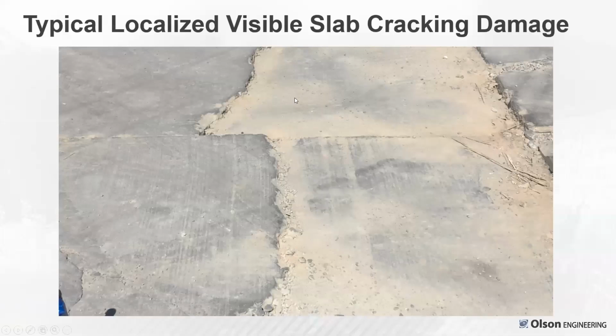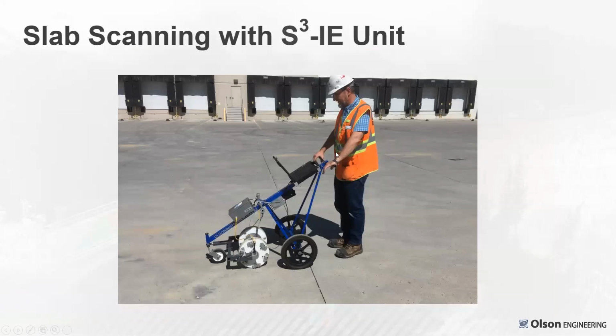This is an example of the slab where they had some subsidence. They actually had to do some repairs here. There was cracking in other areas. These areas were pretty severe where they occurred, but they were very localized. So the concern was, well, what's going on with our slab? Here's me actually out there doing some scanning across this slab with the S-cube unit.